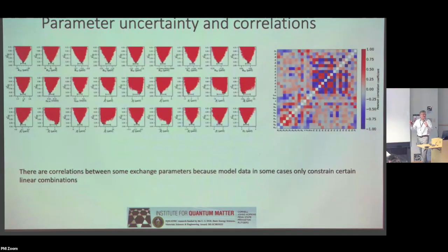Of course, there are correlations between these parameters. There are a lot of parameters. There's also a lot of data. And so what Chris did was that he really spanned this very high dimensional parameter space to try to understand by what accuracy we had determined each of the parameters. And so this is each of the many parameters, and then the criterion for goodness of fit as a function of that parameter. And this again was something you can do with a multi-core processing system, and you can also get the correlation between these parameters. But that is really necessary to make sure that you're not really fooling yourself.